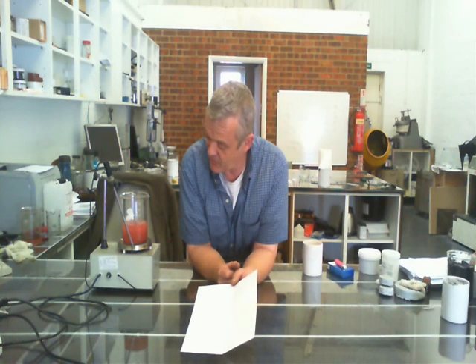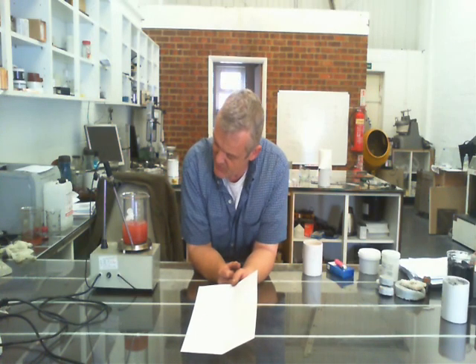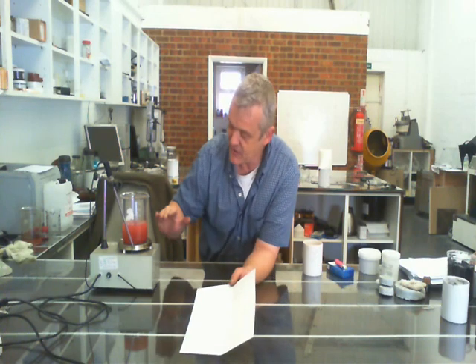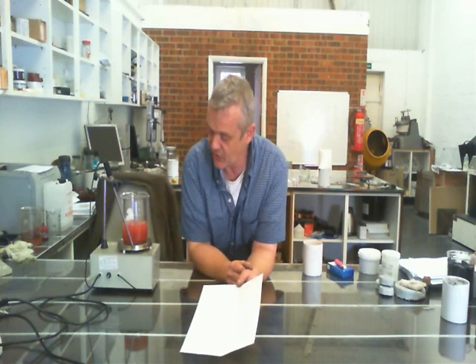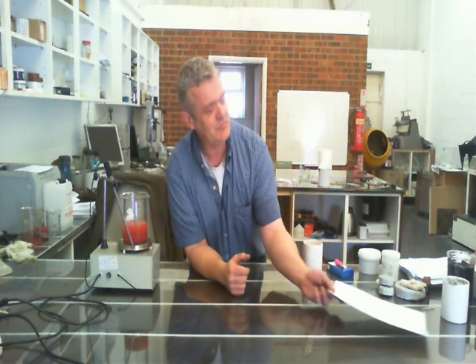Now I'm putting on a mechanical stirrer because it's one of the basic simple pieces of kit that everybody who's got a lab ought to have. But you can homogenize it as well. And it takes about half an hour or so for that to spread throughout the gelatin solution that we've got there, and it will make a brick red solution. Now I've added 10 grams of copper oxide in there, which is quite a lot actually, because what I'm actually after are quite large copper particles.